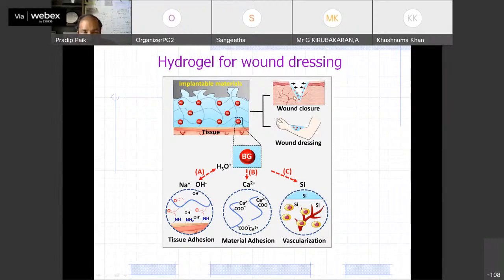This is usually used for wound healing, where, let's say, implantable materials, nanoparticles form. Let's say this is the muscle where a wound was created. You take the hydrogel-based core-shell nanoparticles and fill it with the medicine. After filling, there will be a lot of sodium ions, ionic species, and they will help the adhesion of tissue here and allow this tissue to grow, and they will fill the gap.